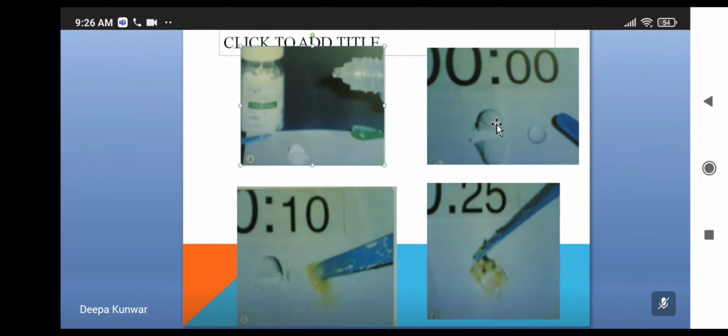At first we should mix the powder with the liquid with the plastic spatula in a folding motion for the first 5 to 15 seconds, followed by mixing the remaining portion of the powder into the liquid for the remaining time. If it's 5 to 15 seconds, then the remaining of the 45 seconds should be used to mix the remaining portion of the cement.